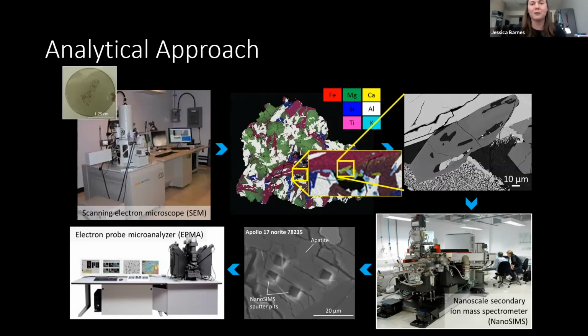You might be asking, why use a NanoSIMS rather than a traditional SIMS instrument? Hopefully the middle figure on the bottom shows you why. NanoSIMS has a much higher spatial resolution than traditional SIMS instruments, which matters for extraterrestrial materials, which are largely going to have suffered some kind of impact history. You can see that clearly in this apatite from a norite from Apollo 17, which is heavily fractured. NanoSIMS has the spatial resolution to allow us to navigate away from those fractures and analyze indigenous material, which is especially important if you're looking at volatiles. You don't want to be analyzing something that's coming from cracks. Afterwards, I'll go to the electron microprobe to get quantitative mineral chemistry data.